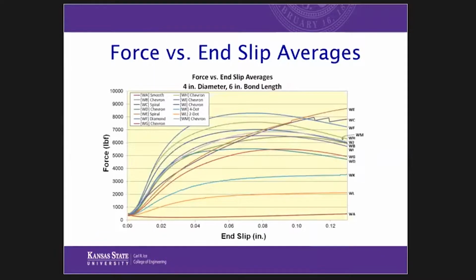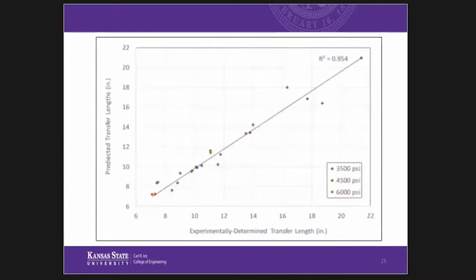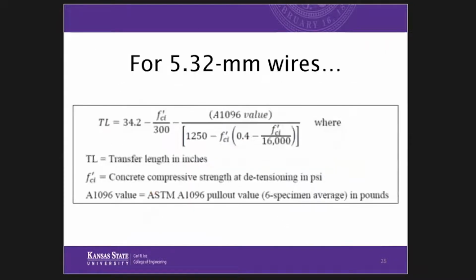When we did this during the development with the different wire types, we were very pleased that for each wire type, we saw a pretty big difference in the bond slip behavior. Not only do we have a difference, but that difference correlated back to the transfer lengths that we measured on the prisms. For the 5.32 millimeter wires, we had a correlation of the ASTM A1096 test with an R squared of 0.954 with respect to transfer length. That's simply transfer length as a function of the ASTM pullout value and concrete release strength.